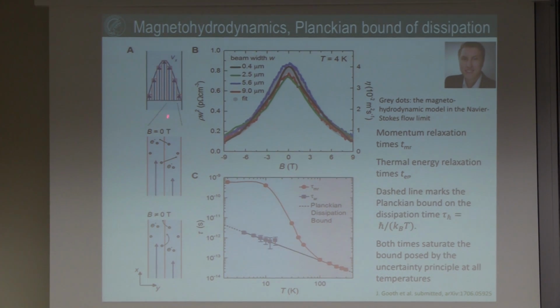So it seems that the electrons are localized in some magnetic orbits, so the profile in a magnetic field looks very similar to the profile we assume in a liquid. And then from this data you can calculate the momentum relaxation time and the thermal energy relaxation time.